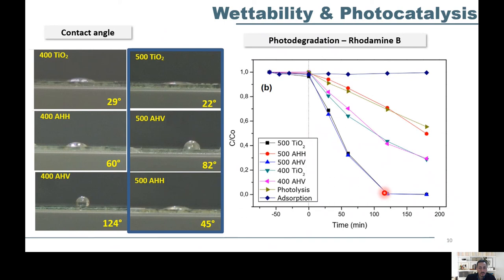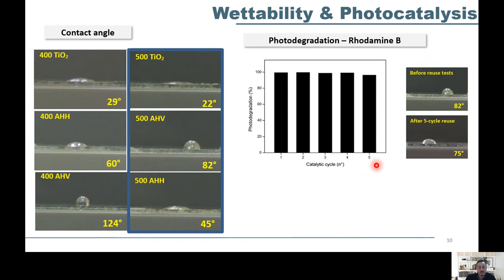Catalytic cycles for the titanium dioxide modified with vinyl agent sample confirmed the chemical stability of the prepared material since the percentage of photodegradation and the contact angle shown here undergo small variations after five cycles of reuse.